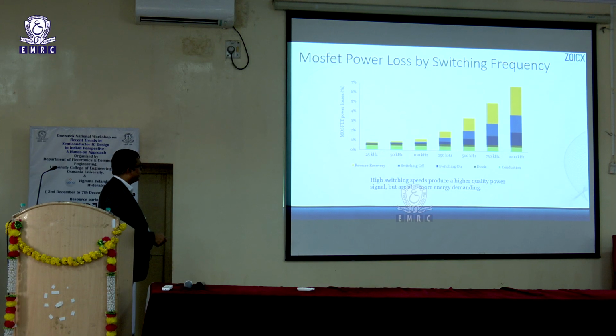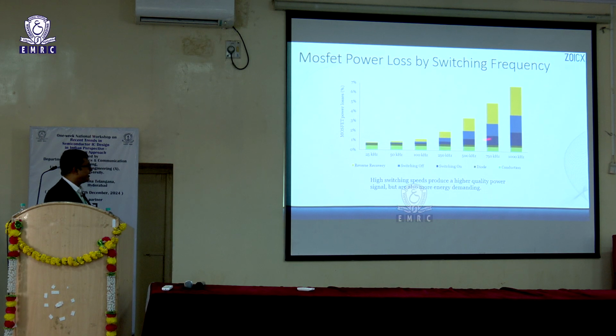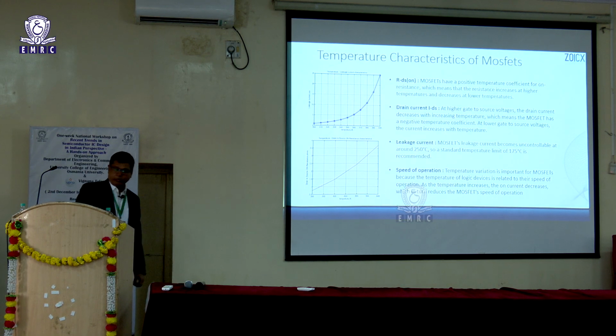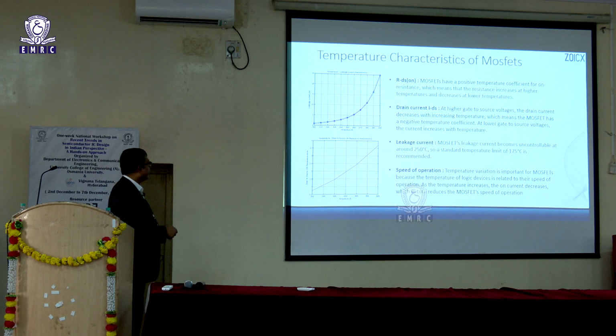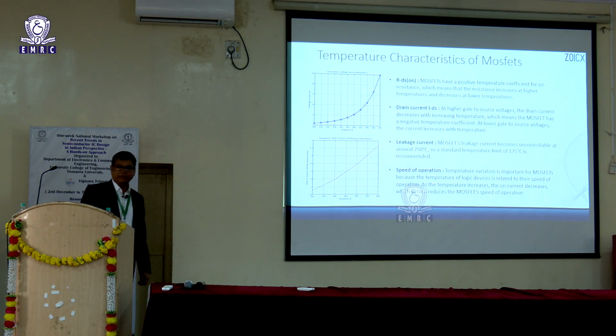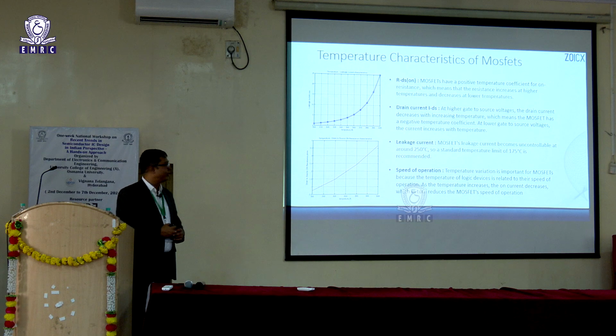As you increase the frequency, you will see that the losses due to reverse recovery or switching off or switching on increase because of the increase in frequency, whereas the conduction losses remain the same. I'm not going to go very deep into it, but one interesting thing you have to notice here is the temperature dependency of the leakage current. So this is leakage current versus temperature. As the temperature increases, the leakage current increases exponentially. That is the reason it is very important that we control the temperature, because once the temperature is beyond a certain limit, the leakage current increases, and then there are losses because of the leakage current. So it is very important that we keep this in control.